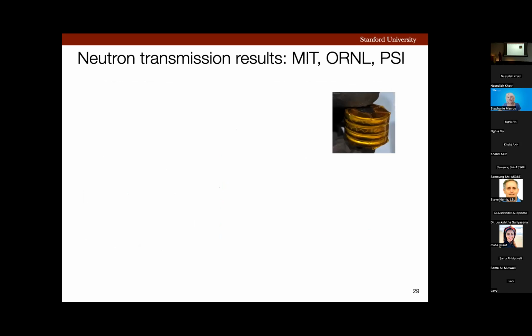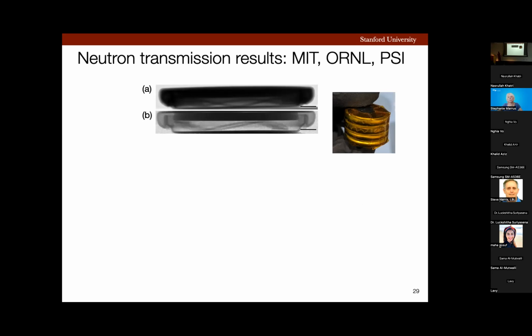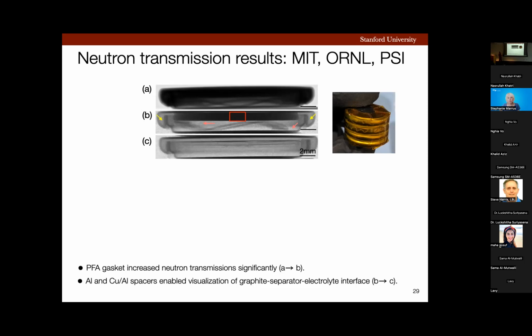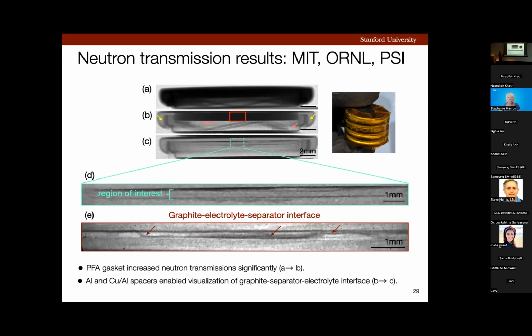results at MIT Nuclear Research Lab, Oak Ridge National Lab, and Paul Scherrer Institute. In this picture, you can see that multiple coin cells were stacked on top of each other for the experiment, which is high throughput imaging. This is a neutron image of a standard battery, which is completely opaque. You can see by comparison, the neutron image of my battery did increase transmission significantly in these regions. Now, this was a result of fluorinated gasket and deuterated electrolyte. But you would notice that the stainless steel spacer is blocking my region of interest, and we cannot see the interface. And therefore, in my final design, when I replaced the stainless steel spacer with an aluminum-based material, I could see my region of interest, which is very clearly visible in this high-resolution image collected at PSI.